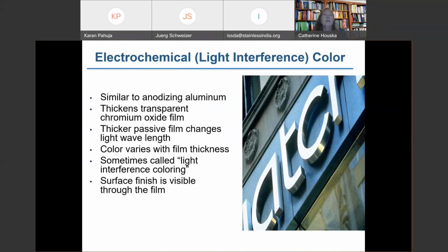Electrochemical coloring is one of the means of applying color to stainless steel. It is similar to anodizing aluminum. It thickens the transparent chrome oxide that makes stainless steel stainless. And as that transparent film is thickened, it filters out wavelengths of light. It's the same thing that occurs when aluminum is anodized. And that's why it's sometimes called light interference coloring. And thicker films give you darker colors.